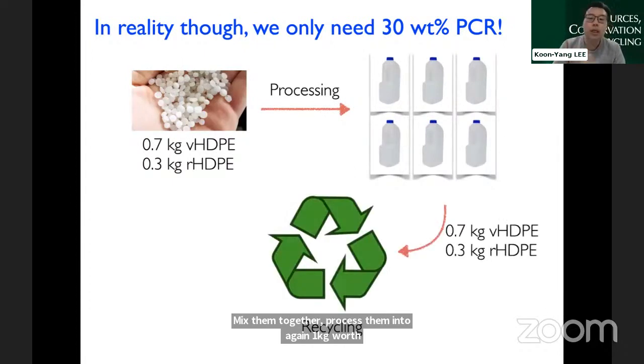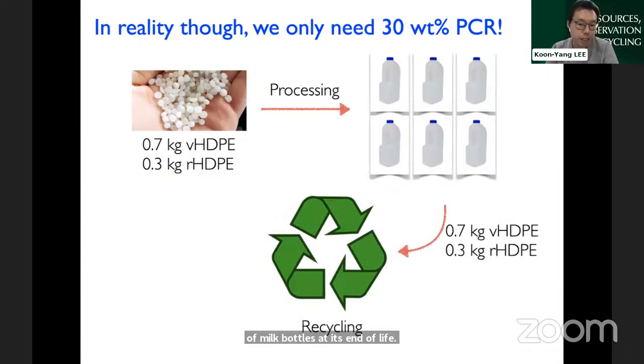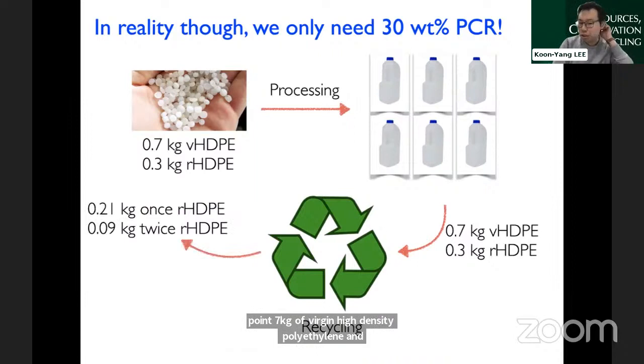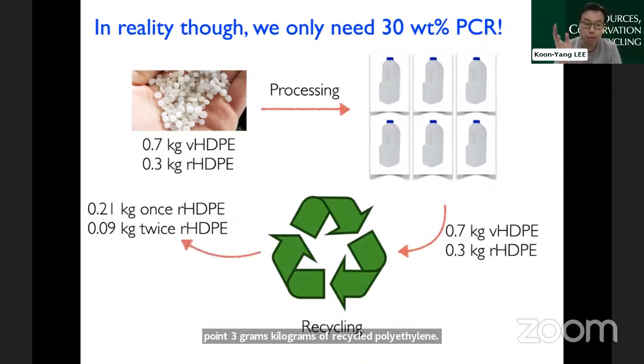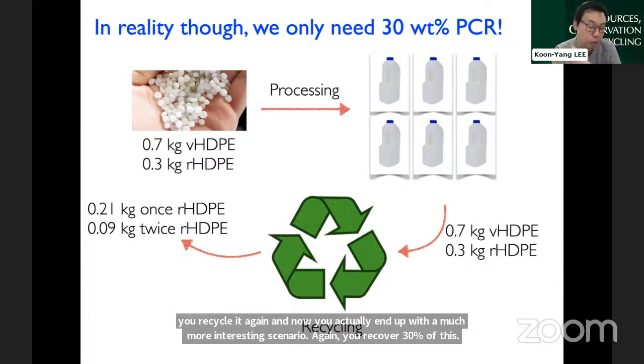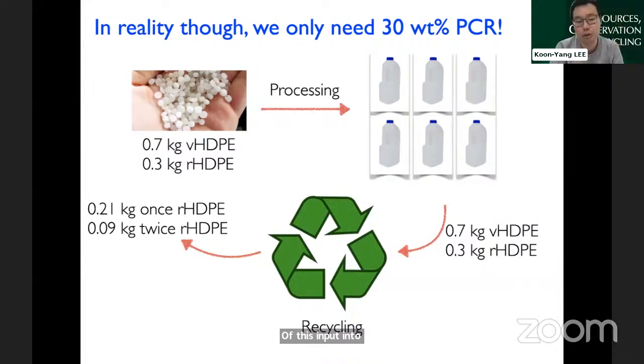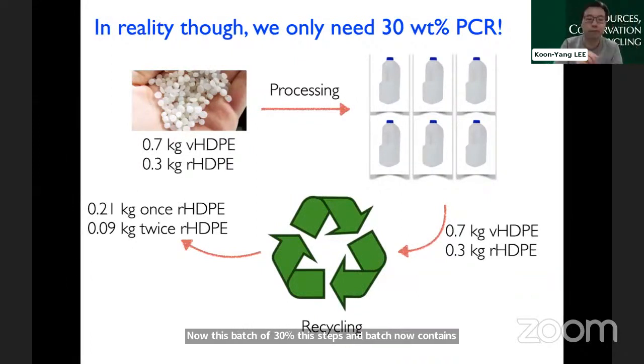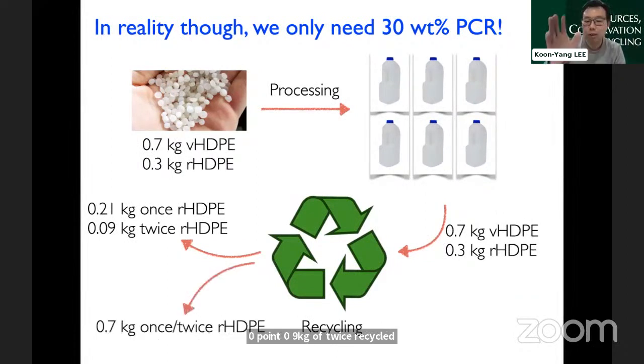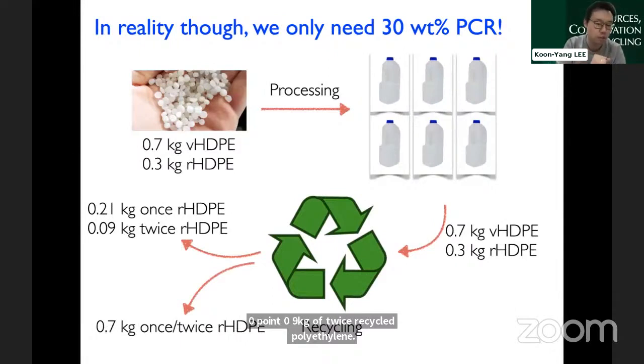At its end of life, you recycle them. In this case, bear in mind that it's 0.7 kilograms of virgin high-density polyethylene and 0.3 kilograms of recycled polyethylene. So you recycle it again, and now you end up with a much more interesting scenario. Again, you recover 30% of this input into a recycling process, such that you can reuse it in your own supply chain again. Now, this 30% batch contains 0.21 kilograms of once recycled polyethylene and 0.09 kilograms of twice recycled polyethylene. Again, the remainder goes to another industry, which is not part of the conversation today.